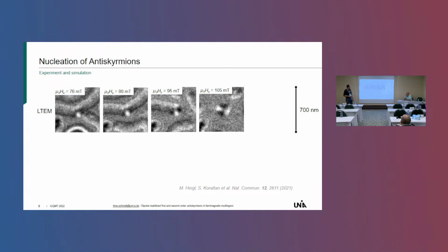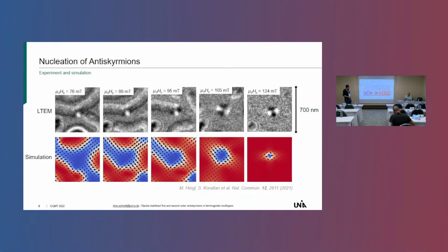With another increase, we are basically there. We've seen it a lot of times at different spots where three domain walls meet and an anti-Skyrmion comes out of that. But we have to experiment a little bit more to qualify that, really. We also have simulations for that, which show a very similar picture for this formation of an anti-Skyrmion.